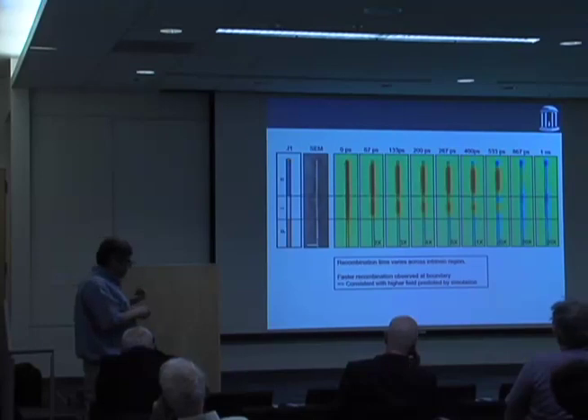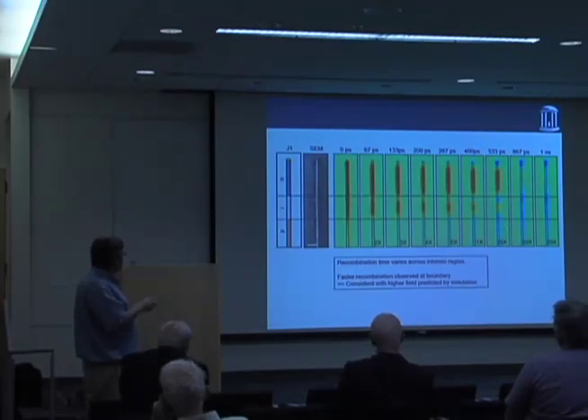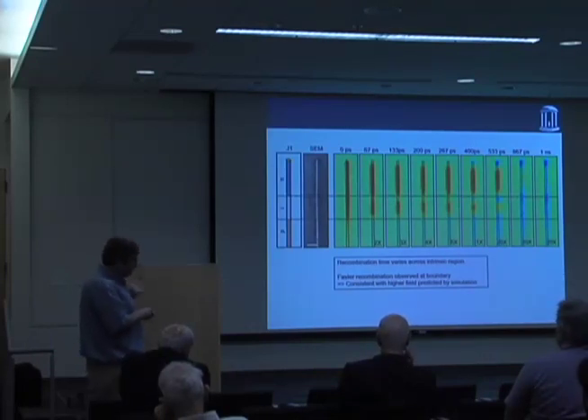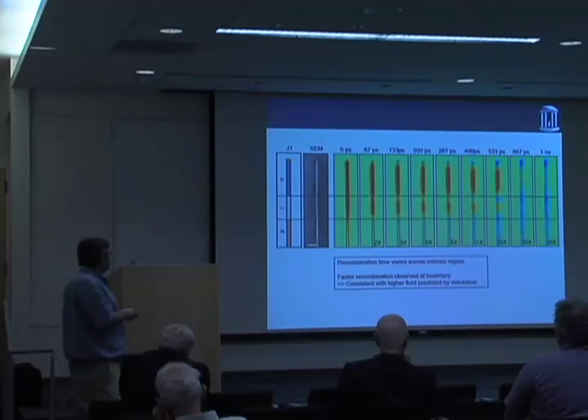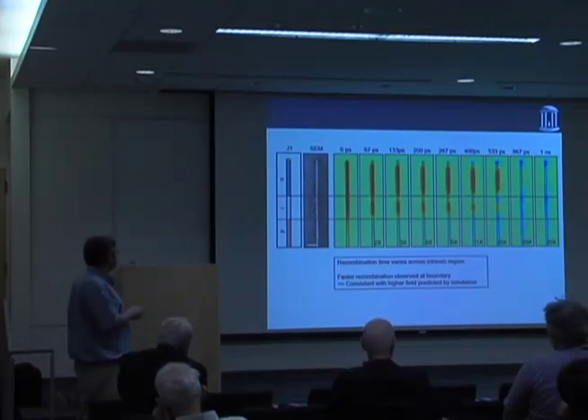Okay, so this is an experiment where we take the pump and the probe, and they're spatially overlapped, and we scan them across the sample. So it's essentially the same type of experiment, but now you can see it in an imaging mode. In the N-type region you see it decay, and in the intrinsic region you see it decay slowly, but in the P-type region it decays faster. What was interesting, and why I'm showing you this plot, is that the signal across the intrinsic region is not uniform. In fact, near these boundaries, you have faster loss of signal. I'm not sure it's necessarily recombination, but you certainly see a faster loss of signal in those regions. And so we started to wonder if that was due to a field that might be established at the boundary. But at this point, that's consistent with, but kind of speculation.